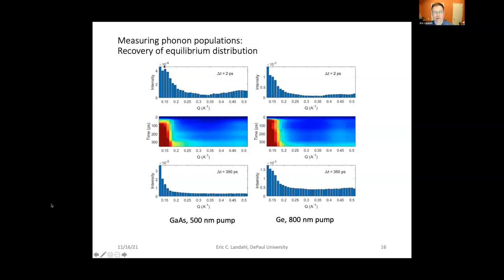Here at 2 picoseconds, we see close to the zone center, of course, an enormous number of phonons, as you would expect down at the center. But then you start to see immediately, halfway out, so at the zone edge, a substantial fraction of signal. And this is in both the gallium arsenide as well as in germanium. This is a time result plot, so you can sort of say this is a line-out histogram as the time increases, going down. And there's quite a lot of interesting characteristics and signals, which again are very reproducible, but not completely explainable. And we have simulations underway.